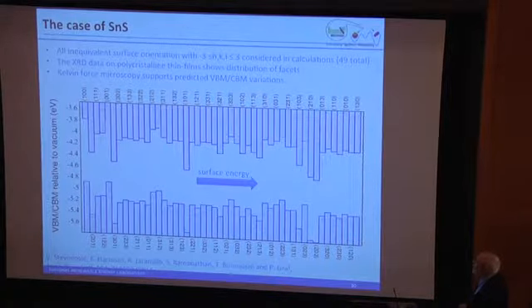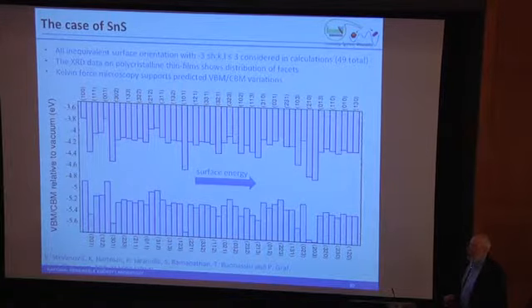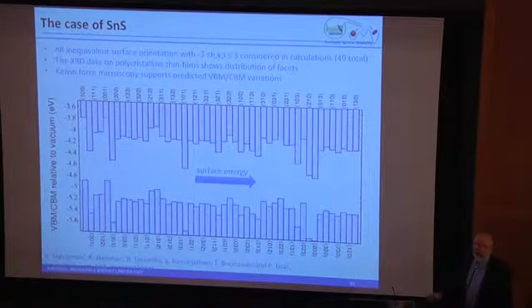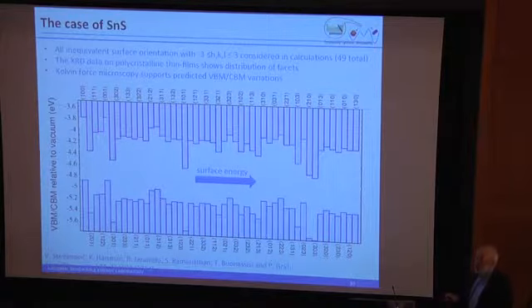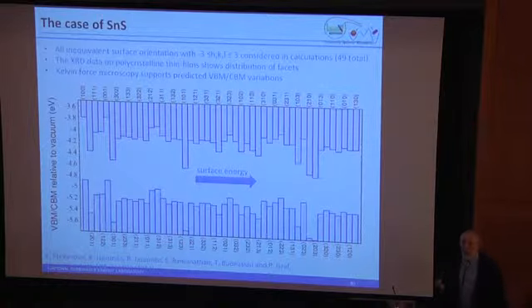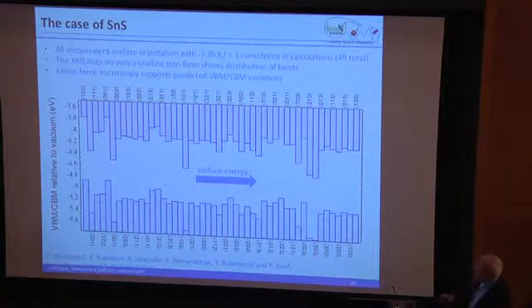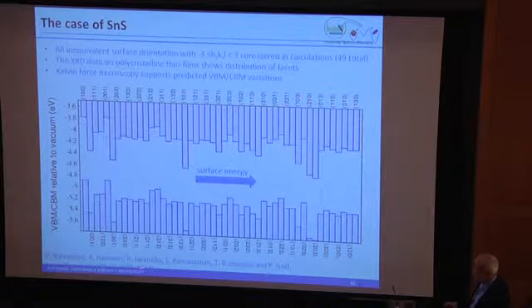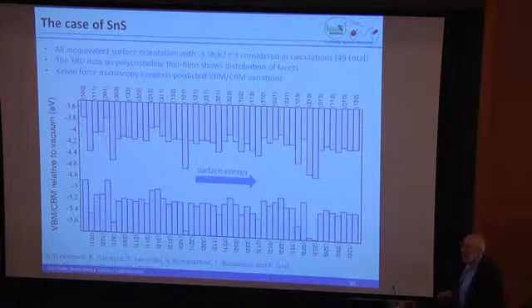So tin sulfide is a new PV material that people are excited about. There's a lot of people, especially Roy Gordon and Tonio Buonassisi at Harvard and MIT, that are beating on this. It's not a particularly efficient system now, but it seemed like a good system to calculate because the surface orientation is very important for that system because we don't know how to make even good ohmic contact to it right now because of all the different surface energies. And so what you can see here, and this is a very recent paper, is that there's a pretty big variation in surface energy across tin sulfide as a function of its orientation.